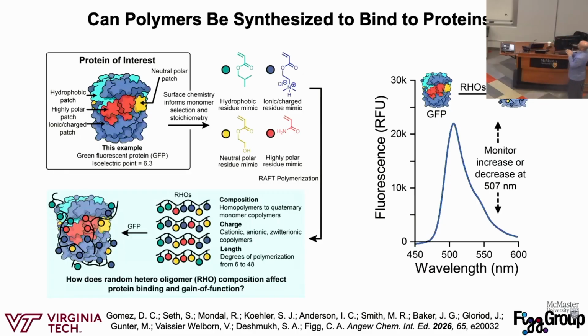So in this first example that I'm going to talk about, we took green fluorescent protein. And what we did is we looked at the surface and said, okay, there are these hydrophobic patches, highly polar patches, ionic charge patches, neutral patches. If we just look at the average chemistry of these patches, can we hypothesize acrylic monomers that would have complementary chemical interactions with these patches on the protein surface?